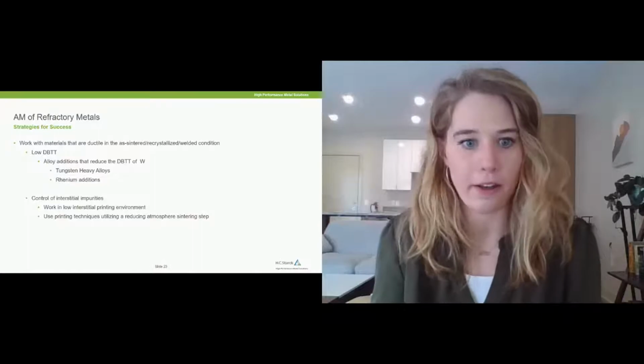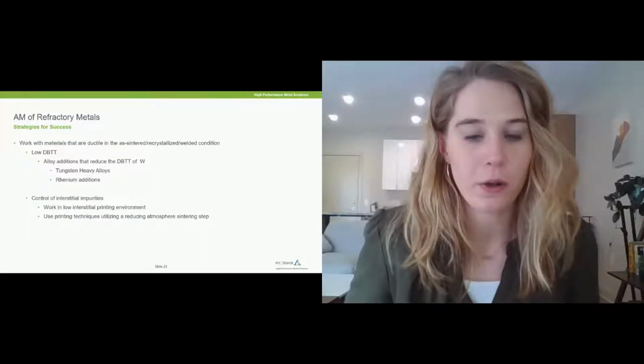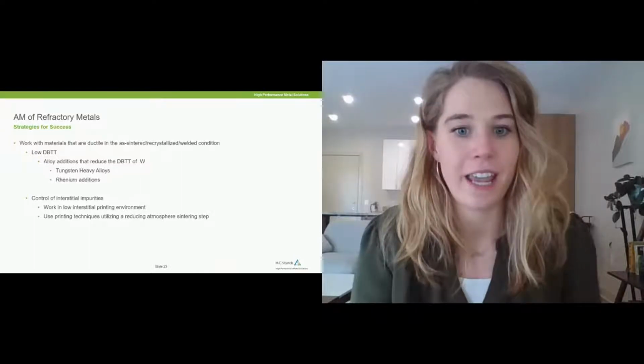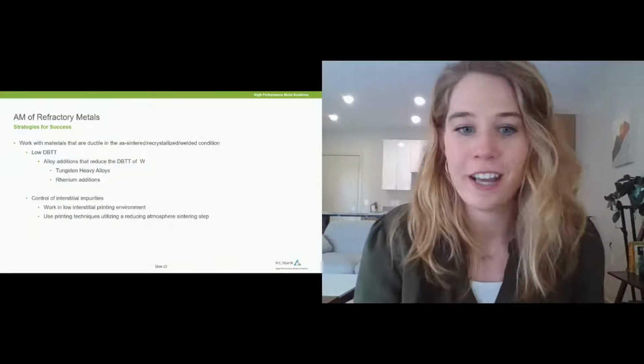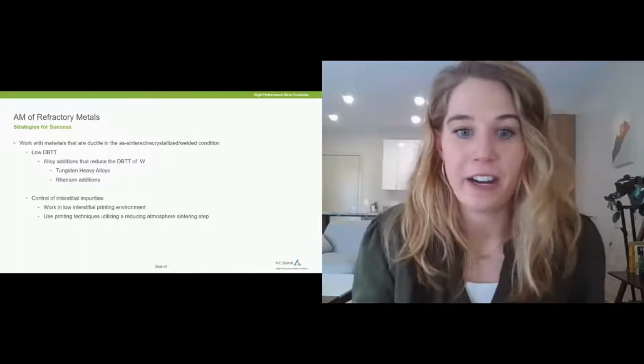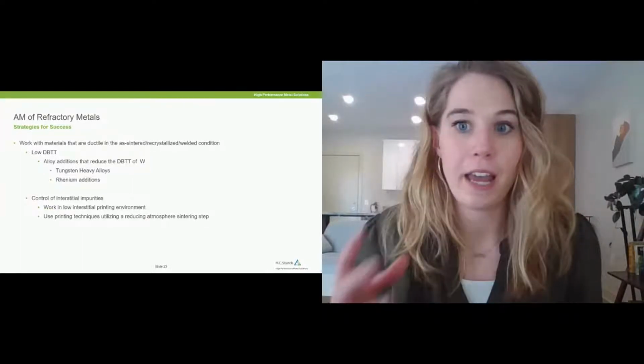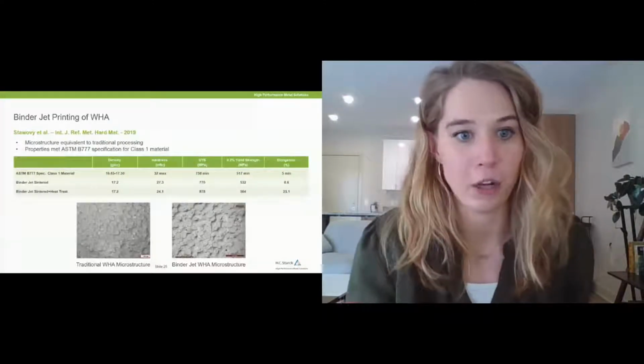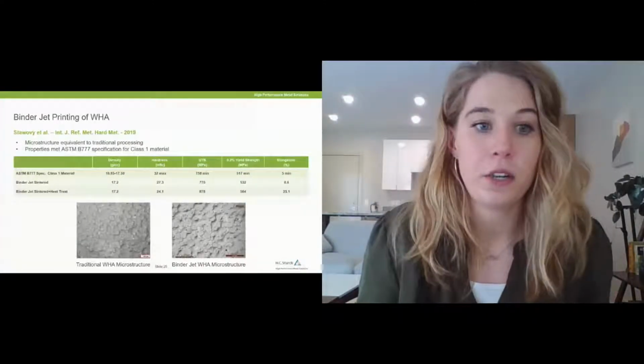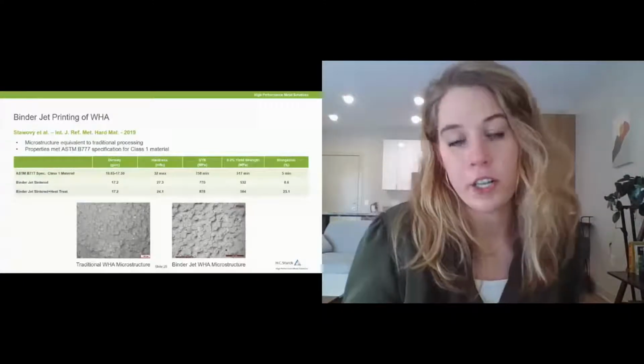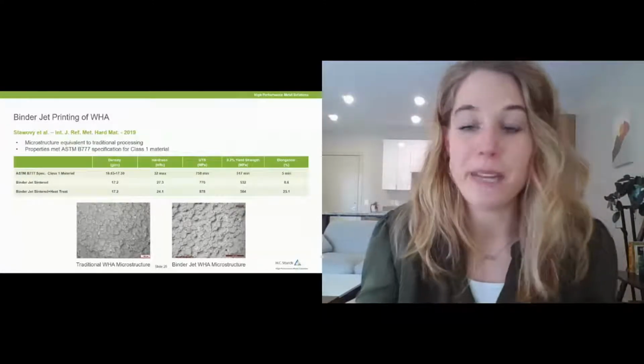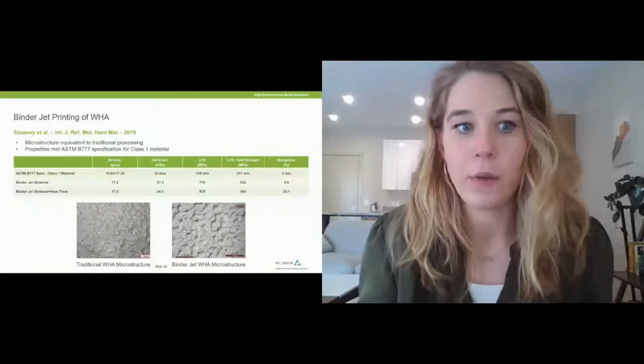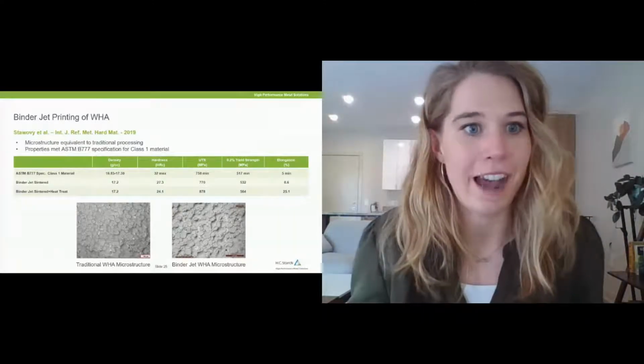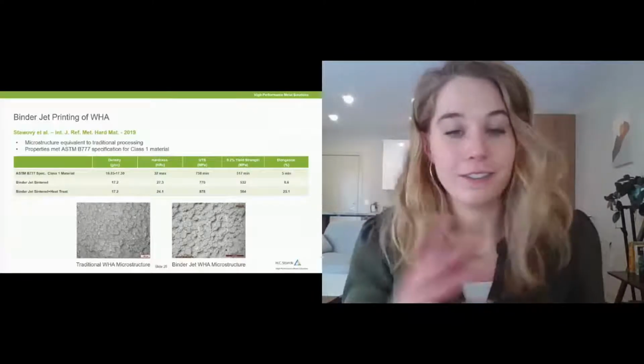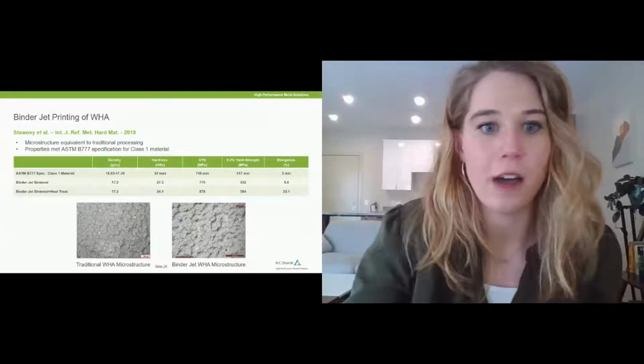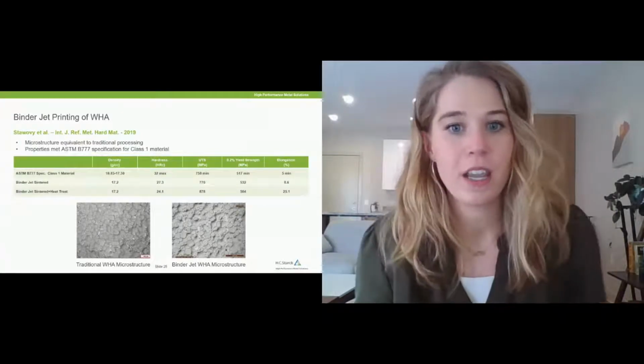Here's just an example of the microstructures, as you can see below, comparing our binder jet tungsten heavy alloy microstructure to traditional tungsten heavy alloy. As you can see, they're very similar, and so that also translates into the mechanical properties. So both in the sintered and the heat-treated condition, our tungsten heavy binder jet solution meets ASTM standards with a little increase of strength and ductility after heat treatment. So there are very great opportunities here moving forward into some applications.